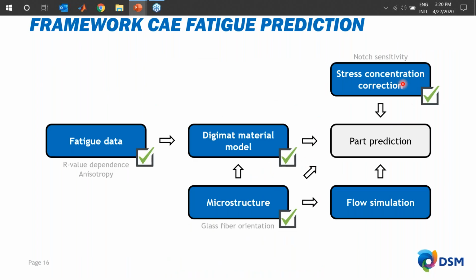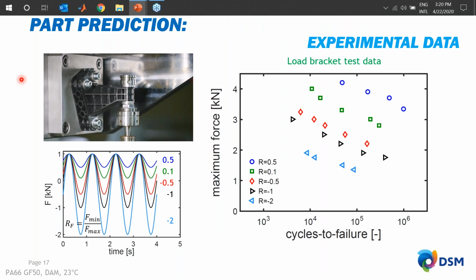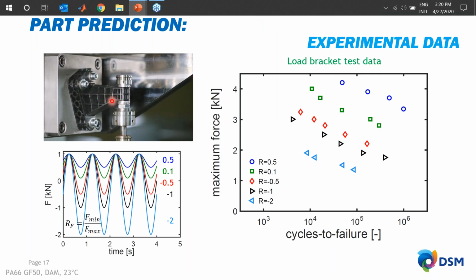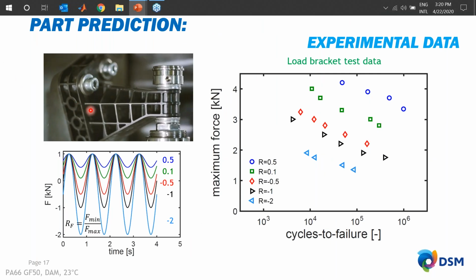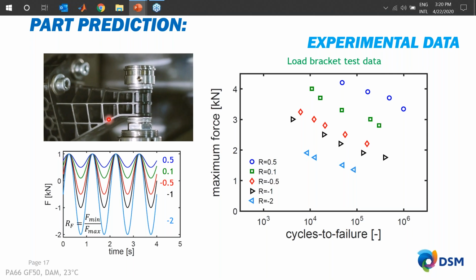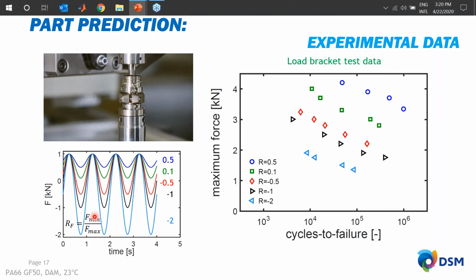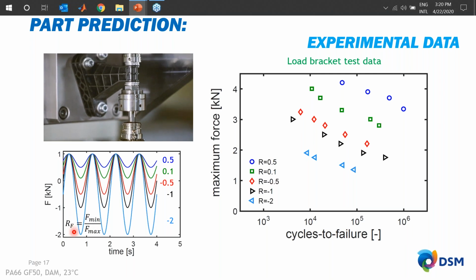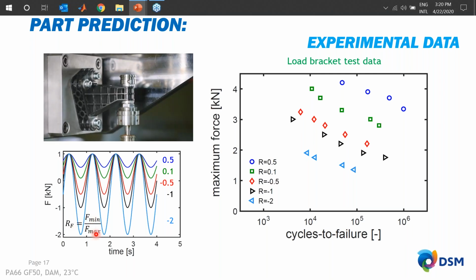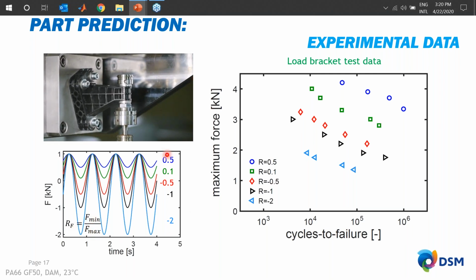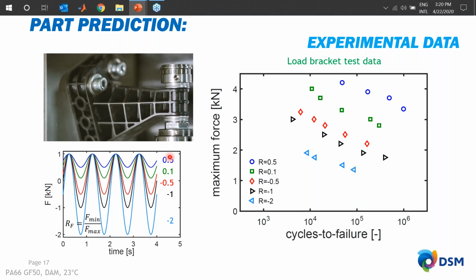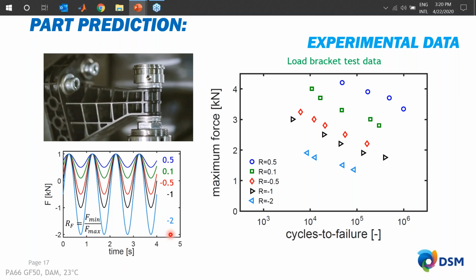So now I hope I also tackled a bit of the stress concentration. The flow simulation I can unfortunately not tackle today in view of time. So the next thing will be the part prediction. Because as I mentioned, we are eventually validating our prediction next to this demonstrator part. So here you can see a movie where we load this part in fatigue, and that means that we apply a certain R value and force. It ranges from the minimum force divided by the maximum. I try to go for a large range of force R values, ranging from 0.5 to -2, and then we end up with these kinds of SN curves.